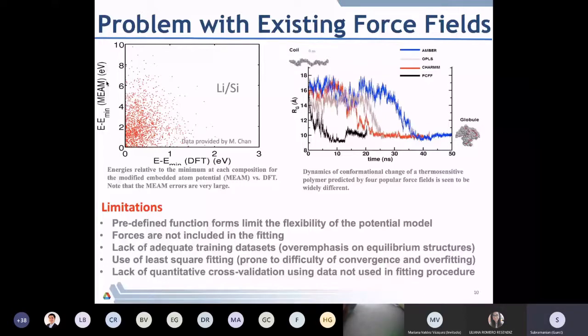If there was a correlation between the model and the DFT, you would have actually seen this lying on a straight line. But the scatter just tells you how bad this force field is. And that is one of the problems that we face when we are dealing with more complex systems, especially ones where there are mixed ionic-covalent characteristics such as lithium silicon.